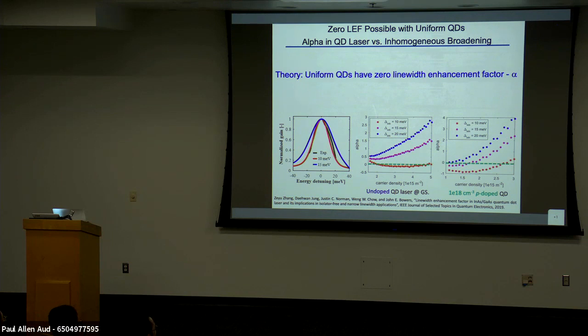That's a reflection-insensitive device. And again, intuitively, what is coherence collapse? It's that you get a reflection back in the cavity, it changes the number of electrons, and in response to that, it changes the phase of the cavity. And if that cavity is long and far enough away and long enough Q, that's coherence collapse. But if alpha is 0, there's no phase change. You can change the reflections back all you want, and there's no phase change. So this is for undoped devices. You can get down to here. If you actually p-dope it, which is good for reliability, right? Good for high temperature gain, then you actually can get not just positive alpha, but negative alpha as well. And so that's why quantum dots are less reflection sensitive.